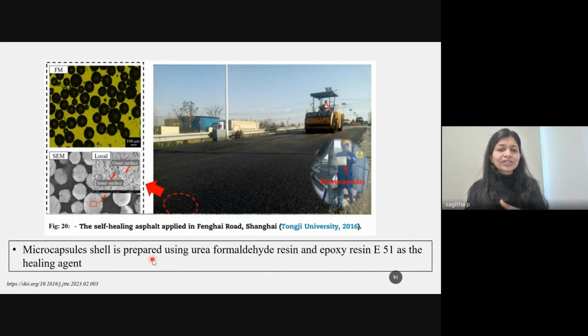So the shell morphology or shell structure can be prepared using different types of polymers, and we can encapsulate the functional healing agents in that. And for this particular application, they prepared the shell using urea formaldehyde resin, and the healing agent they used was an epoxy resin which is E51 based. So these are some applications of self-healing agents, and how nanoparticles take part in the self-healing process, everything.